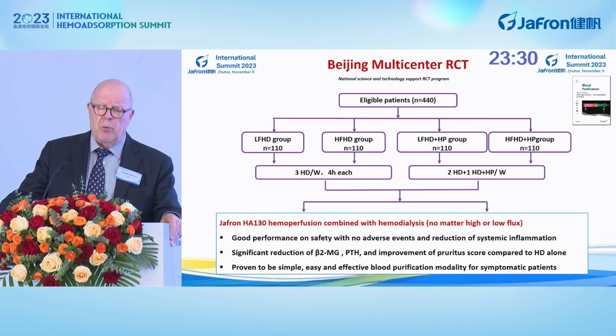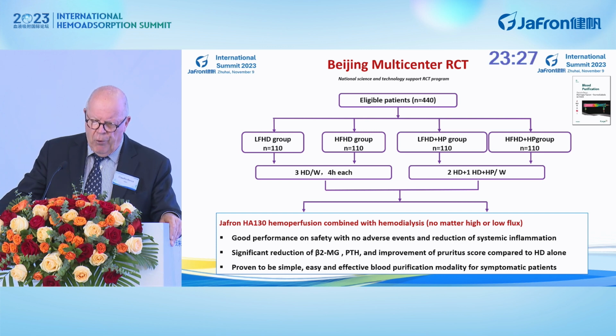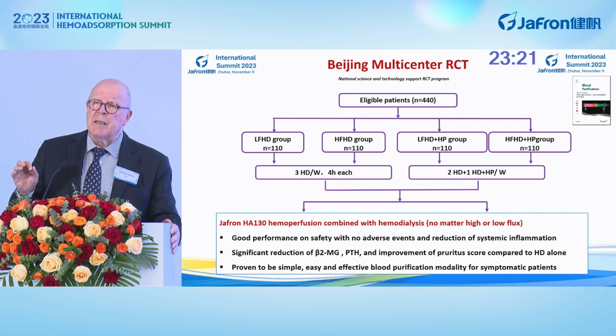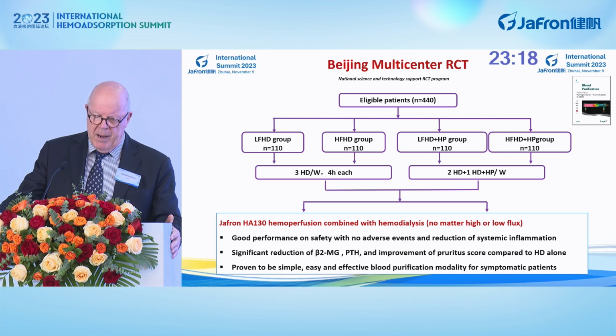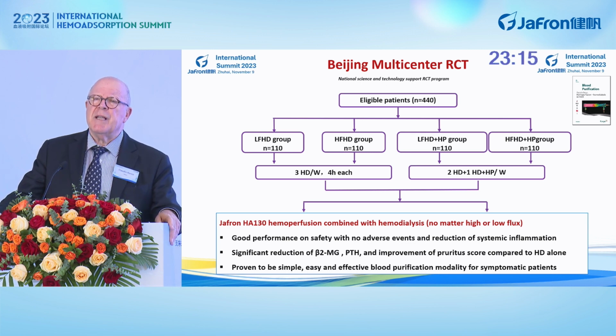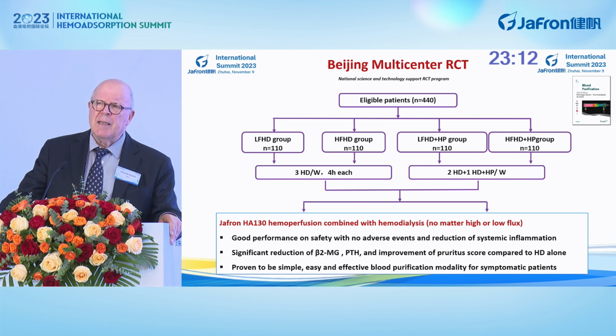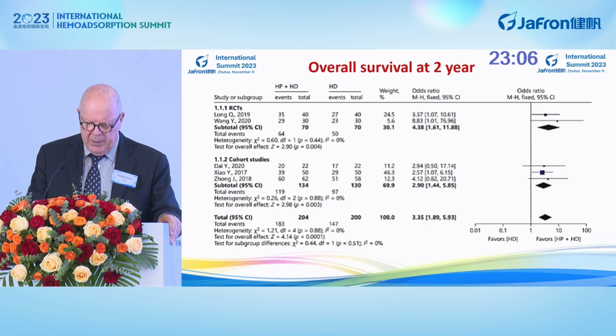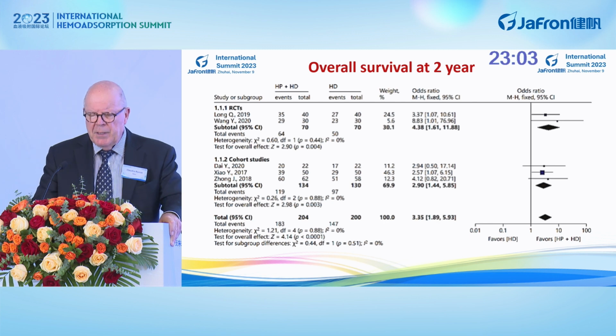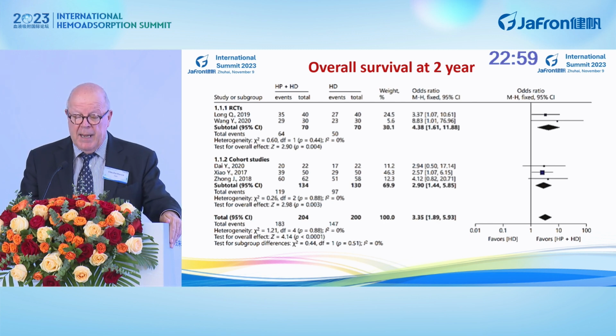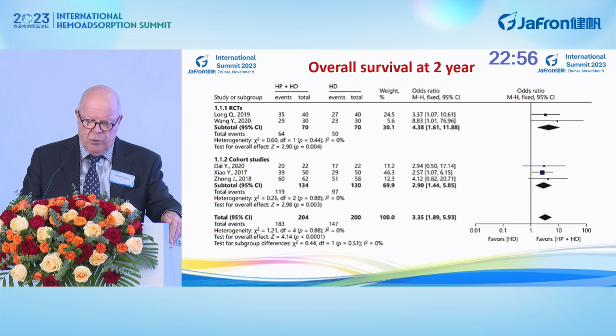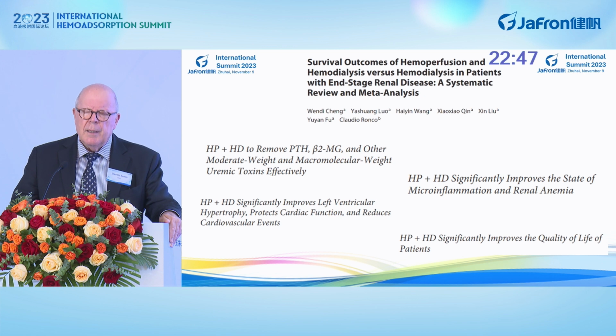And there is another study from Beijing that was done on more than 400 patients who actually compared the same type of group, but using also high and low flux membranes. And what they found was that when you use adsorption, the results are achieved independently of the use of high or low flux membrane. So we did a recent meta-analysis, and the overall survival at 2 years, even in randomized trials or cohort studies, seems to favor the utilization of the combination of hemoadsorption plus hemodialysis.